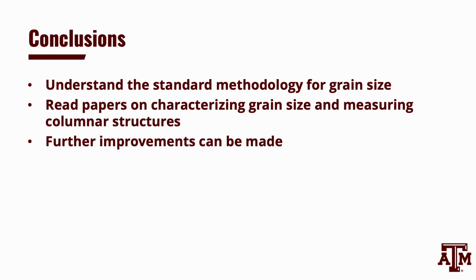Over the course of this work, I examined the standard methodology for grain sizing in equiaxed grains. I found out that these processes do not work well for columnar grain structures in AM materials. I read papers by Leto and Imhoff on characterizing grain size and measuring columnar grain structures. I like the number density method for measuring columnar grains, but I feel like it would be complicated finding the nucleation sites and the grain boundary within the cast. I could see how this is useful for me in my area because a lot of applications of AM are in biomaterials and biomedical devices.